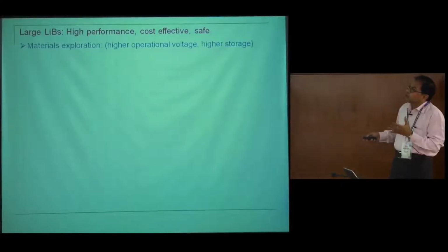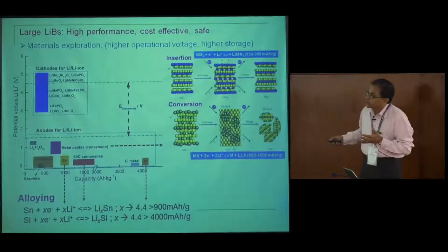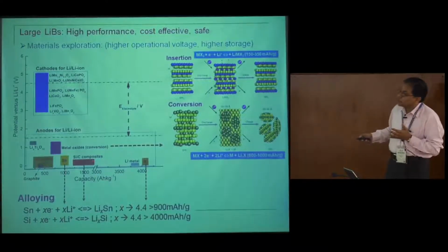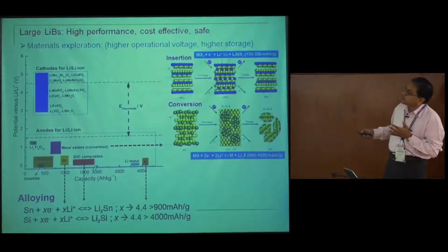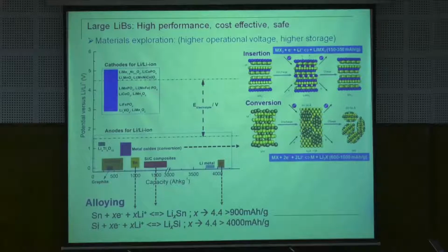So using the same chemistry, people have gone into materials exploration, looking at higher operational voltage systems. And they've built this kind of a Ragone plot where, starting from carbon, people have moved to alloying systems, conversion systems, and they've used even higher voltages by varying the transition metal composition in the solid state compound. The important thing to keep in mind is that the HOMO-LUMO gap of the electrode should be in between the degradation voltages of the electrolyte. So this has been one way of increasing the performance of the system.